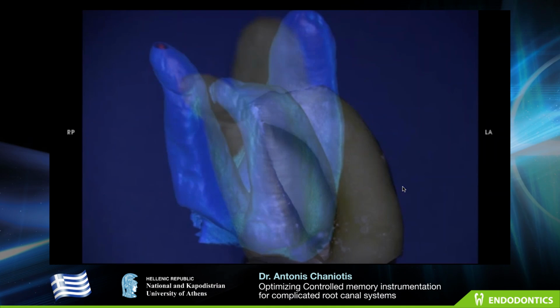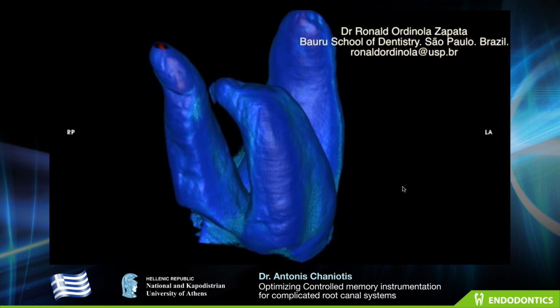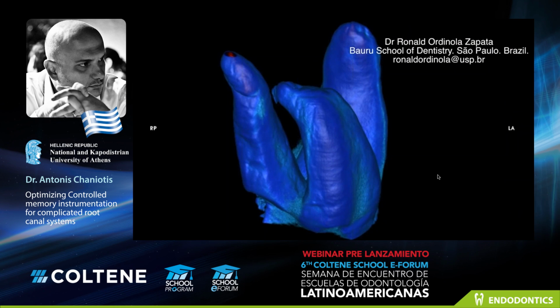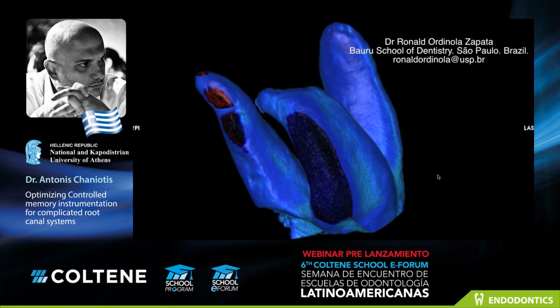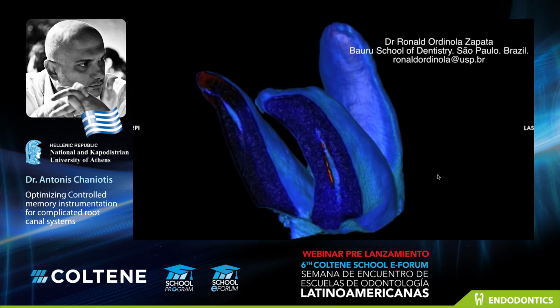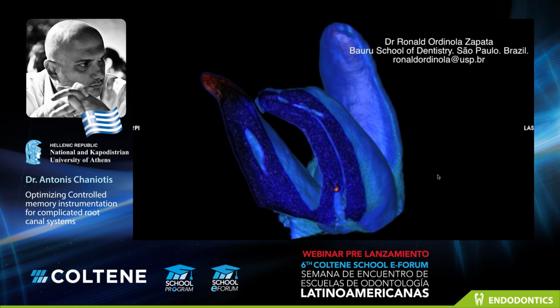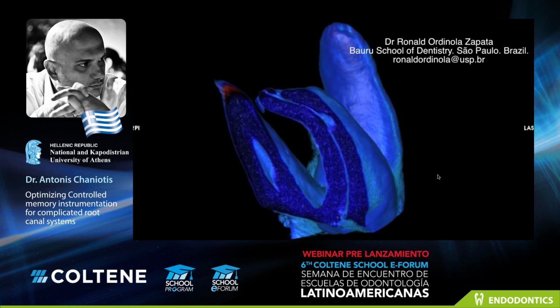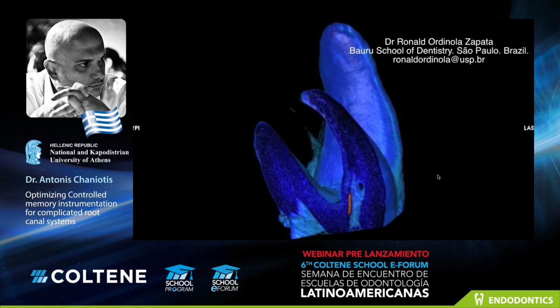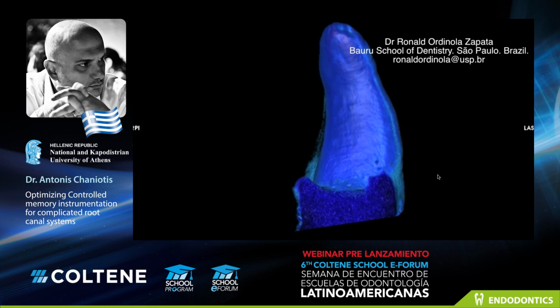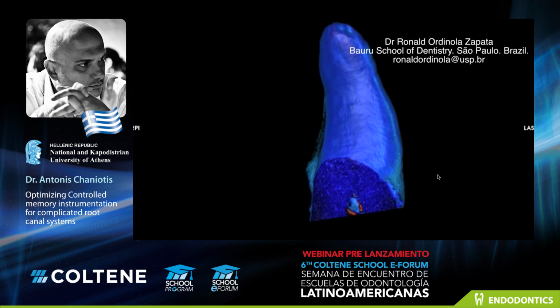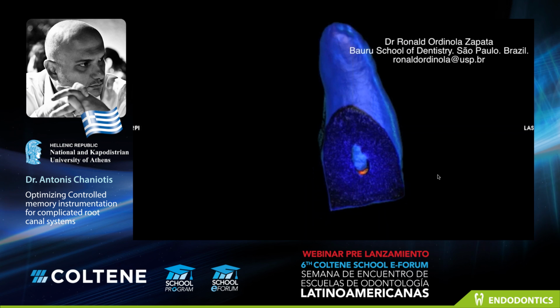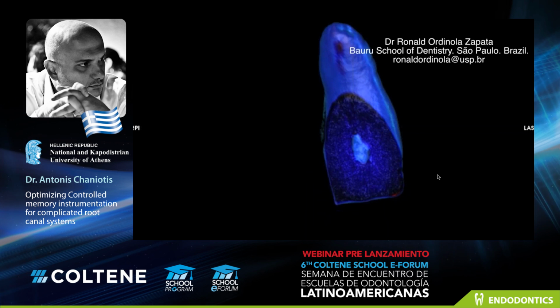I sent this extracted, highly curved tooth to my friend Ronald, who was in Brazil back then, and he made this fantastic micro CT in order to find out what went wrong with the instrumentation in this case. And you will clearly see that the problem was that the canal was ledged. So the doctor couldn't negotiate around the abrupt curvature, tried for 5 subsequent appointments until the tool fractured, collapsed, and the tooth was extracted. We don't want your instrumentation of highly curved cases to end up in Ronald Ordinola Zapata's micro CT because of failure to navigate around the anatomy.